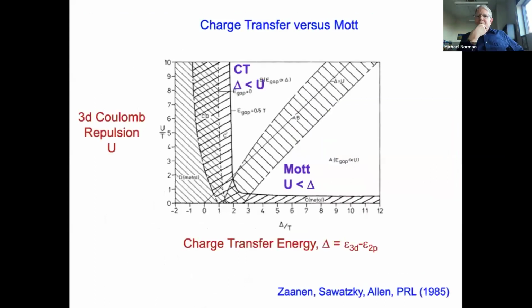And so to get perspective on this, I bring up the famous Zaanen-Sawatzky-Allen phase diagram, where you have a charge transfer energy between the transition metal 3d and the oxygen 2p states, and then you have the Coulomb repulsion. And so if the Coulomb repulsion is less than the charge transfer energy, you're in the Mott regime. If it's greater, then you're in the charge transfer regime.